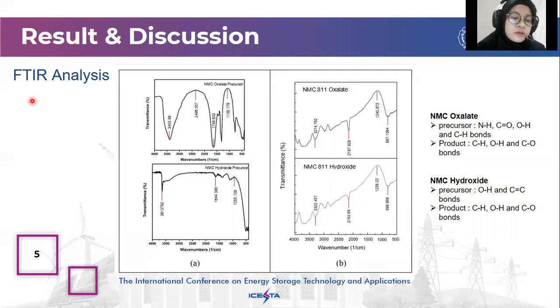The next slide shows the result of the FTIR analysis to determine the bonding that occurs in the precursor and the product of NMC. The result shows that the NMC oxalate precursor indicates nitrogen bond to hydrogen, and carbon with a double bond with oxygen, and oxygen bond to hydrogen, and carbon bond to hydrogen.